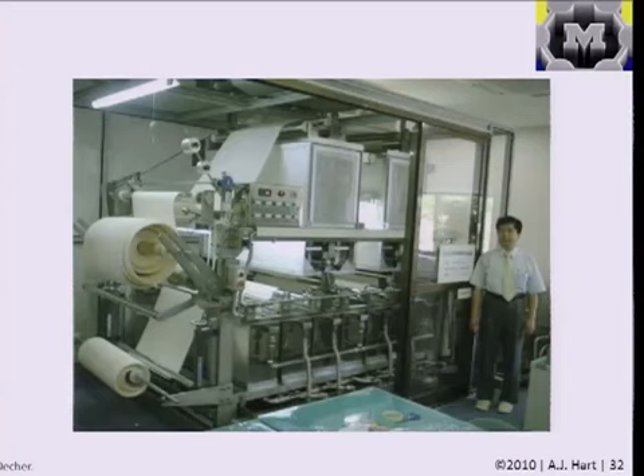an example from a company in Japan where they're coating essentially a paper substrate or generally a thin film by sequential LBL, by dipping the paper into different baths of desired solution. So some of these are probably the rinse, and some are the desired A and B components. And it also appears that the film goes up and down a couple times, and up and down again. And what's probably happening up here is they're drying the film after the rinse step, so it's ready for the subsequent film deposition. So this probably takes this film through the desired number of coatings and then collects it on a roll and uses it for a particular application.